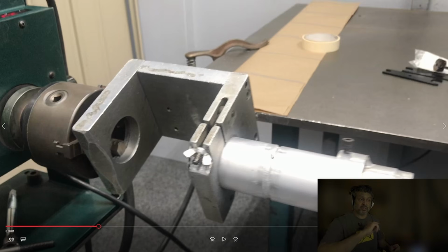If you just hit the pedal and continuously move the part, you will 100% get porosity. And that's how I failed it 7 times. I would get the puddle ready and I thought, okay, if I move it really, really slow, I won't get any porosity. No, you have to almost completely come to a standstill and just move once you see the weld puddle go down. And when you do that, the penetration on the inside will be beautiful. It'll be 100% uniform. I wish I had pictures of that. Unfortunately, I don't, but you get the outside.